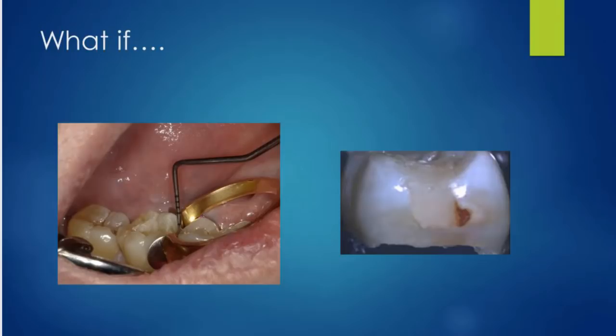But now, what if you are in a situation where, as I said, you have more than 4 millimeters from the bottom of your proximal box to the height at which the composite needs to be placed on the cavo surface? In this case, you can see that we're at about the 6 to 7 millimeter mark for the total depth of that proximal box. So I would never, in a case like this, want to inject the entire preparation.